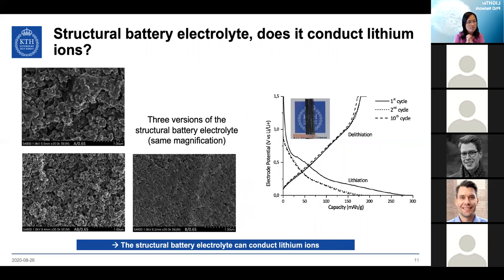Here we see SEM images of 3 different versions of the structural battery electrolyte, where we can see a sponge-like structure of the polymer phase. This is showing that the phase separation is at a small scale. In order to check whether lithium ions can flow through this material, we tested the battery functionality. The graphs show that we are able to fill and remove carbon fibers with lithium ions when they are inside the structural battery electrolyte.